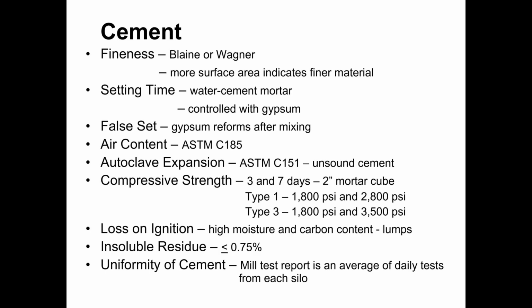A good rule of thumb is that if cement has hardened lumps in it, that's an indication that it has been exposed to moisture. If you can break up those lumps with finger pressure, then the amount of moisture exposure is not too high. It's acceptable. If you cannot break up the lumps with finger pressure, then the moisture exposure has been too high, and that cement sample, that cement stockpile should be discarded, and new cement should be used.